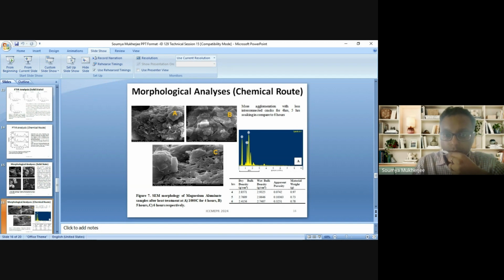If we observe the morphological analysis, the 4 hour heat treated sample is much more dense, while the 5 and 6 hour samples have some cracks. It may be due to the presence of the fuel that we are utilizing, since the fuel evaporates out with the heat treatment. So sometimes some froth is there which may create that porosity, in contrast to the solid state process, where there is a tendency to get a more agglomerated structure.